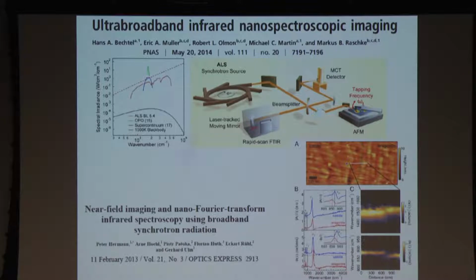And then a paper came up in 2014 from Markus Raschke and Hans Bechtel and Michael Martin, and they combined a home-built system based on a Bruker spectrometer and a Bruker AFM. They combined that with their ALS synchrotron, and they get a very nice broadband spectra here. In this case, they looked at a biomineral, and they could see here very clearly the interface, in this case, between calcite and aragonite.